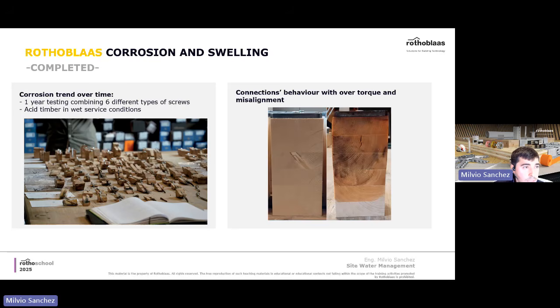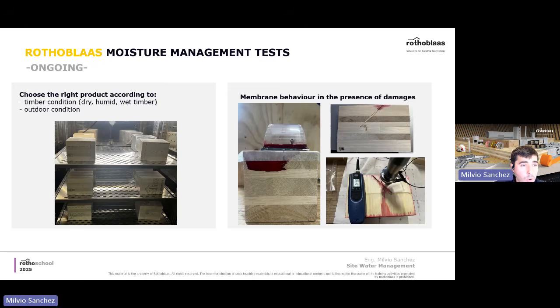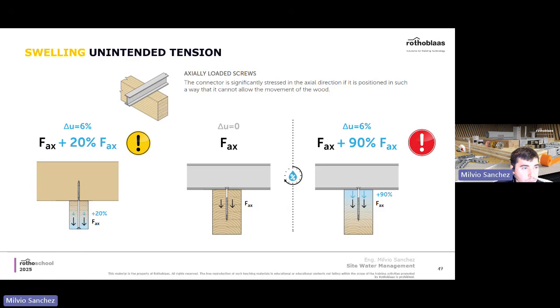In other research that we have done, we assessed swelling as well, with different configurations, misalignment, and acidic timber in wet conditions, because depending on the wood species, it matters a lot. The corrosion may be more or less significant depending on the wood species. And ongoing now, we are studying membrane behavior in the presence of damage: what happens if water goes inside, and if you have a breathable membrane, how much time it will take for the moisture to escape the CLT, and the difference between types of membranes.